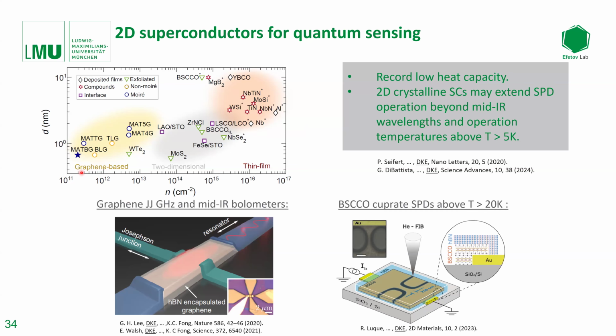And the other thing which is really nice about these superconductors is that they're all extremely low density. Because, as I mentioned yesterday, twisted bilayer graphene has a carrier concentration which is extremely small. So here, the per-sheet carrier concentration is only 10^11 in the superconducting state. And this is orders and orders of magnitude lower than in traditional superconductors, which are usually good metals.